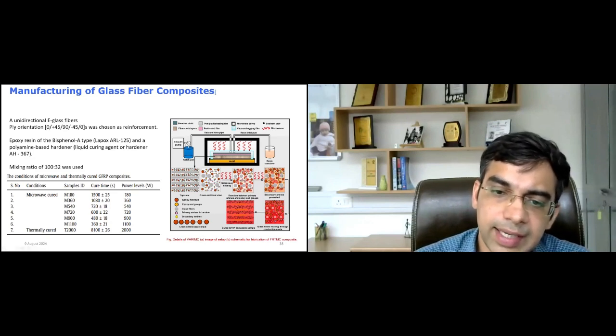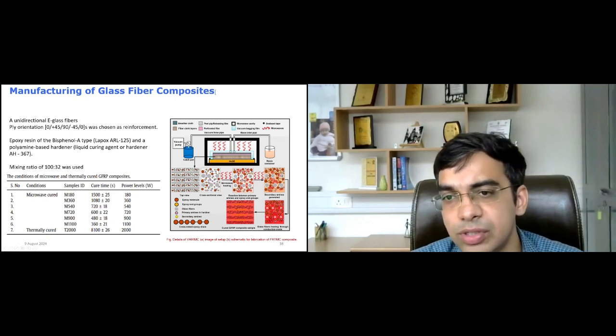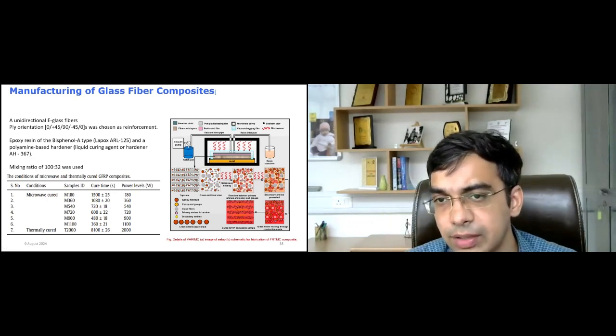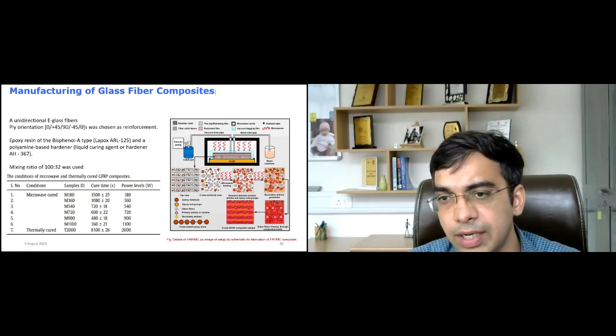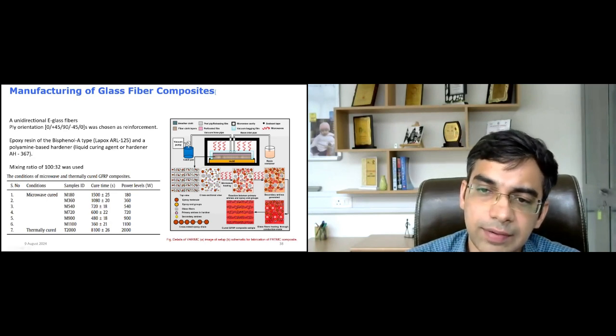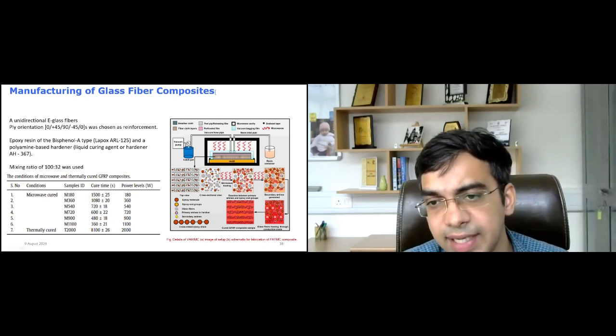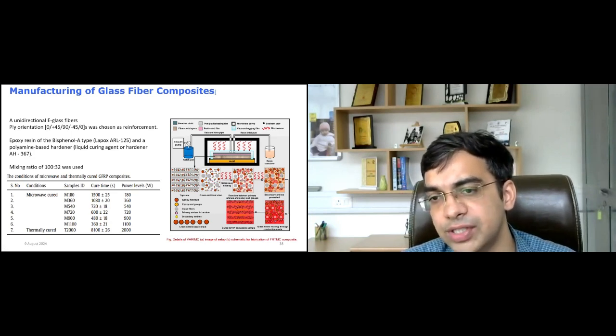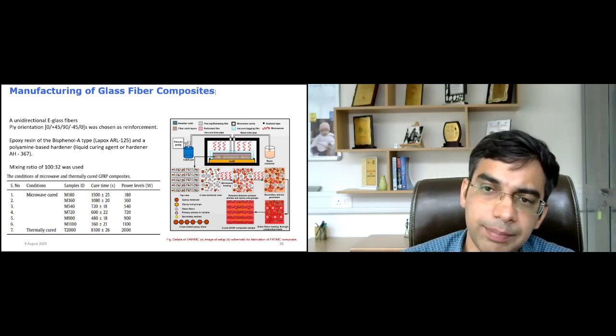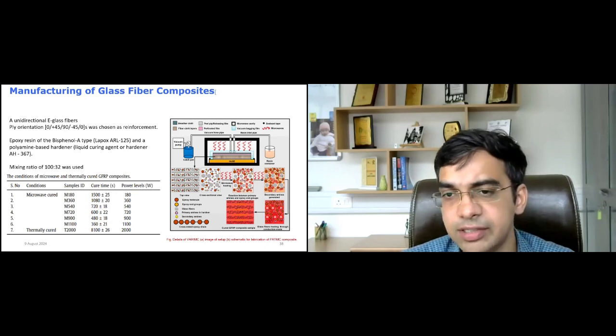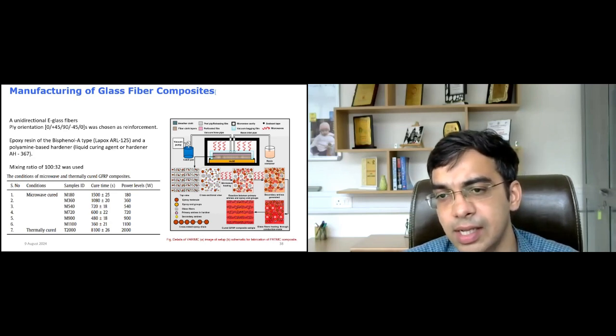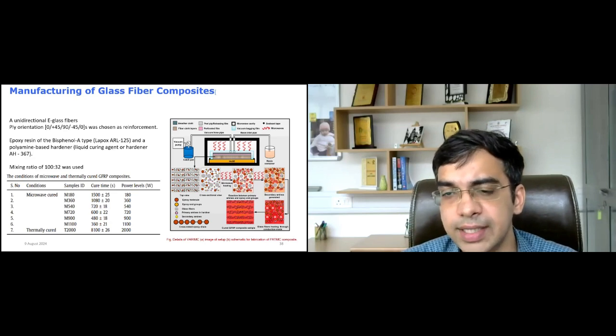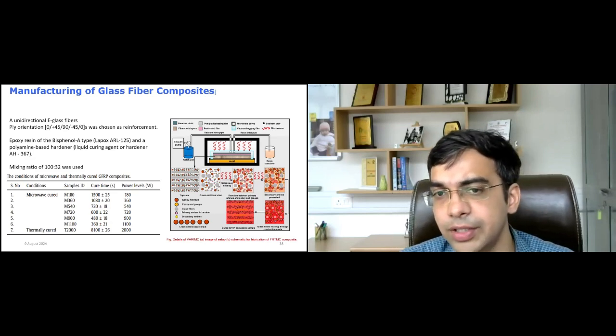And now to understand the mechanism, how curing takes place when we expose such composites to microwave. So what we have done here is basically we have tried to utilize a vacuum bagging arrangement coupled to a mold which is made up of Teflon. So Teflon is chosen here as the mold, unlike metallic mold chosen in other manufacturing processes, because Teflon is basically microwave transparent. On top of it, we have put in the vacuum bagging arrangement. This is the industrial vacuum bagging arrangement as utilized in other manufacturing processes. In the similar arrangement, the epoxy is brought in as the vacuum is developed in the vacuum bagging arrangement.